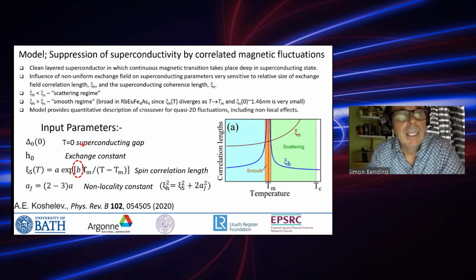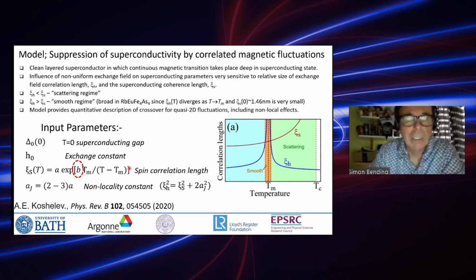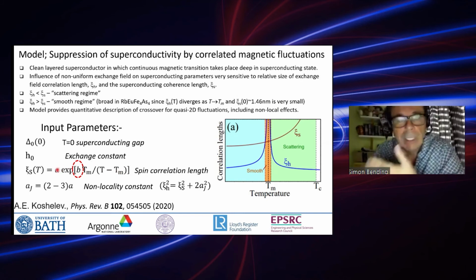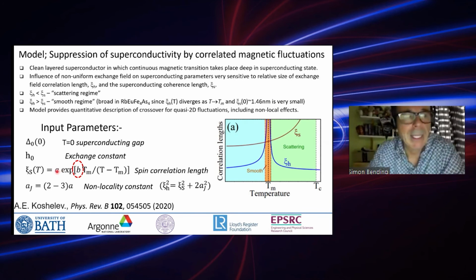The first is the superconducting gap at T equals 0, delta naught. We have to put an exchange constant into the theory, h naught. We have to describe the magnitude of the spin correlation length, which is given by this expression, which you can see is diverging at the magnetic ordering temperature Tm. A here is the interatomic spacing of the europium atoms in the AB plane, so that's already defined.